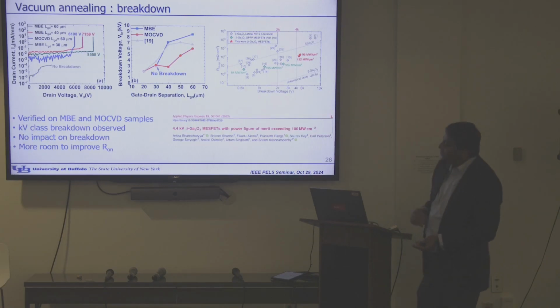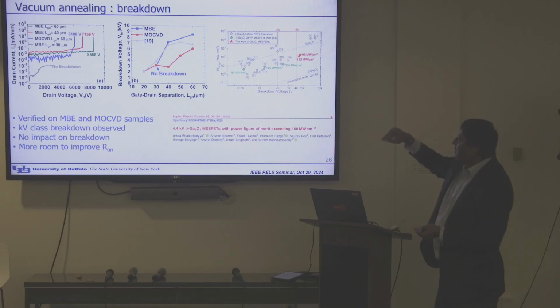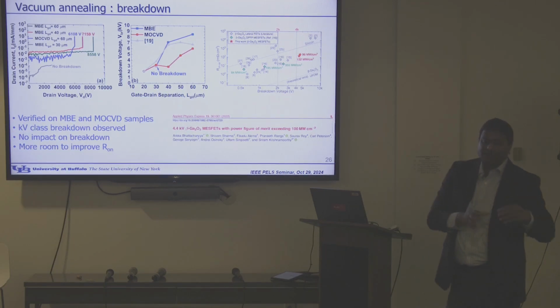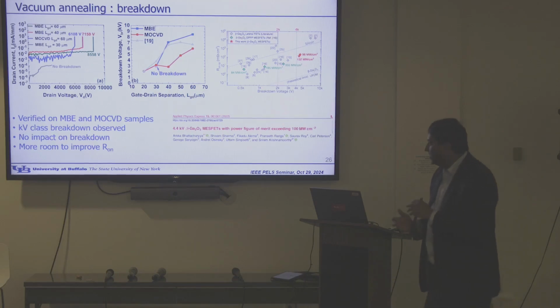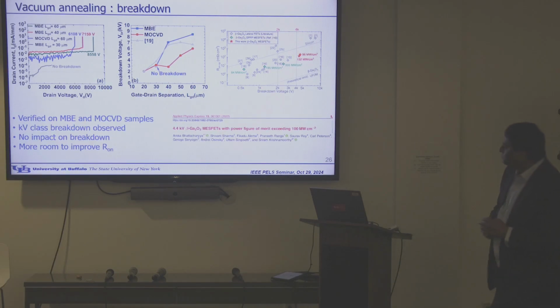Right? Now what about the breakdown? So we improve the resistance. Is the breakdown same? Yes, it is same. You can see on the left here, different breakdown voltages. The center figure again explains that, the gray triangles, the previous generation, and the blue ones, blue and red, were the new one with the annealing. You can see they're all similar. So we're able to recover the resistance, but not degrade the breakdown voltage. Usually, what happens when you try to do one, the other one goes bad.